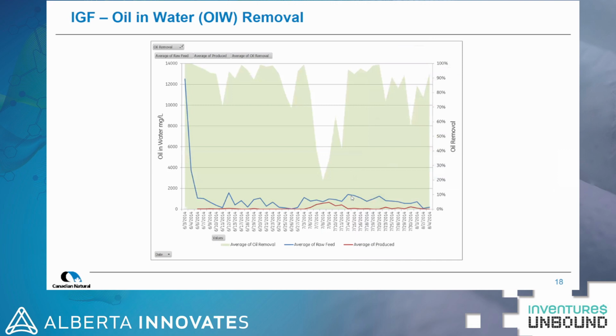What's shown here is the performance of the IGF. So it was able to consistently remove over 90% of the oil. There was a dip in the middle, and that's actually when the chemistry was turned off. So it showed the value of the chemistry step upstream of the coarse de-oiling. Our target was less than 20 ppm in the treated water from the IGF, and in the effluent from the coarse de-oiling step, and we were able to achieve that.